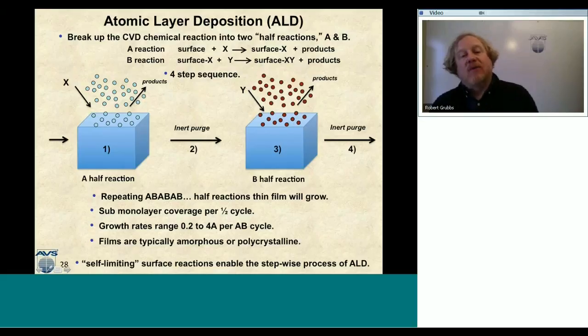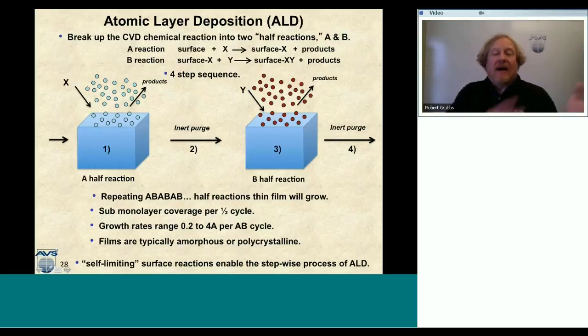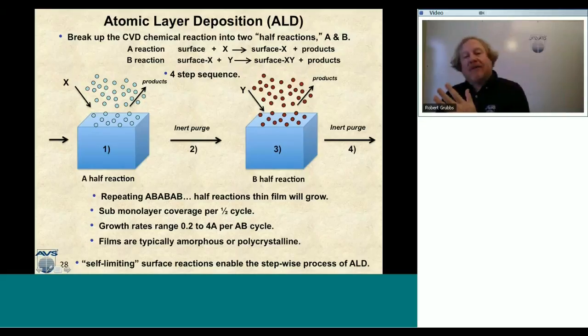Reactant Y reacts with the precursor X on the surface and produces products. And when that reaction is complete, then I go to my 4th purge step and I remove all the Y reactant from the reactor and all the products, and then I repeat. So in atomic layer deposition, when I run these AB sequences, these half reactions, then I'll actually see a film